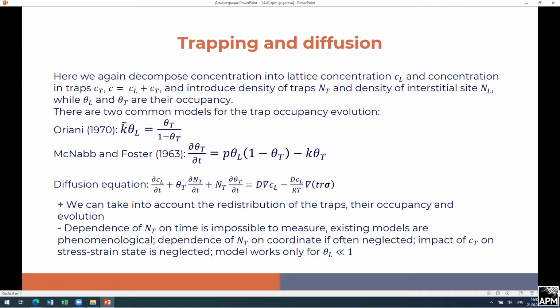So we use the McNabb and Foster equation, which describes the dependence of the occupancy of traps on time and occupancy of the lattice, where P and K are some material parameters. So finally, we write the diffusion equation for our case for linear expressions, and again we can solve it numerically.